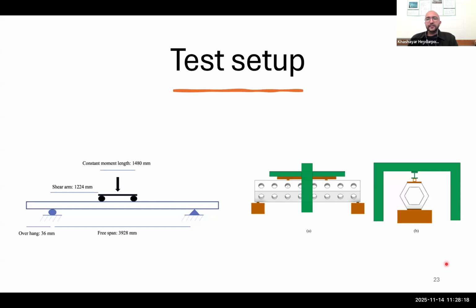So right here we have the 4-point bending test setup in this figure, where we can see that the overhang length is 36 millimeters, and we also have the shear arm of 1,224 millimeters. And no strain gauges were attached to the specimen.